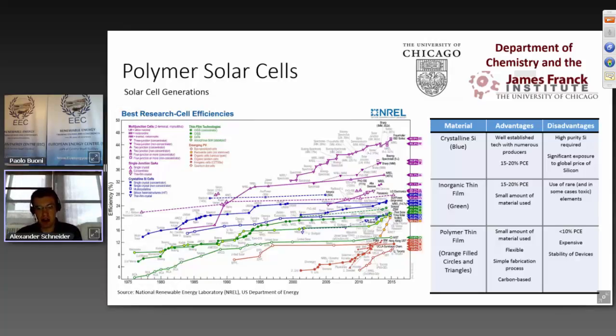Now, unfortunately, these do have drawbacks, which have made it so that they're still within the realm of the laboratory right now. They're relatively inefficient, so we've just recently broken the 10% PCE barrier. They're expensive, so even though in the long run they have the potential to come down in price, I think a lot more than the inorganic thin films, right now they are currently expensive, and that's made commercial optimization hard. And the stability of devices is a common issue, in that some parts of these devices are attacked by air and moisture, which requires them to be encapsulated in order to have similar lifetimes to what consumers would expect.